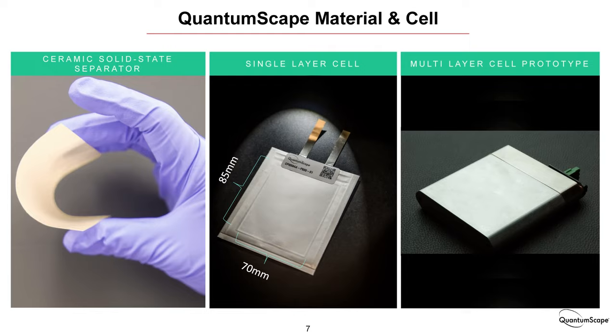Because that ceramic separator is a material that allows lithium ions to propagate through it at about the same rate as they do through today's liquid electrolytes, but it prevents lithium metal from penetrating it. And lithium metal, of course, is what dendrites consist of. So that basically allows lithium ions to go but stops dendrites.